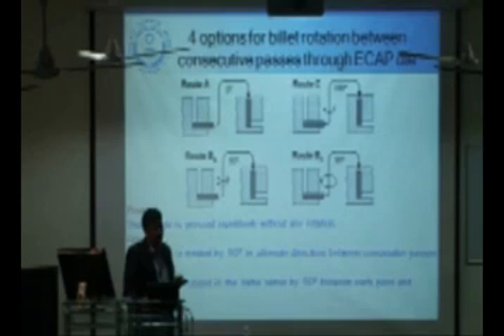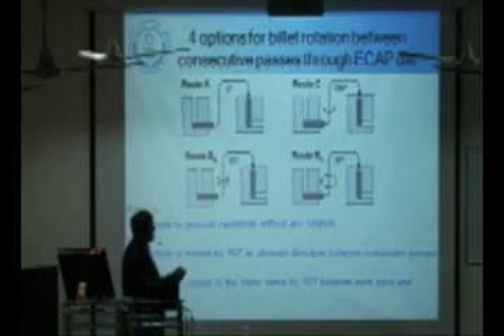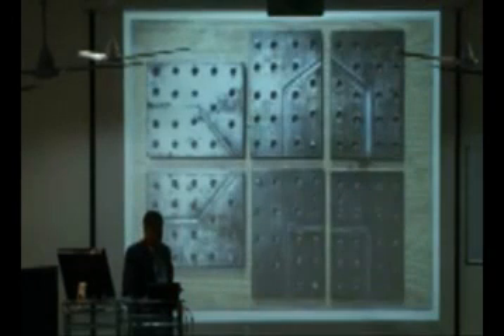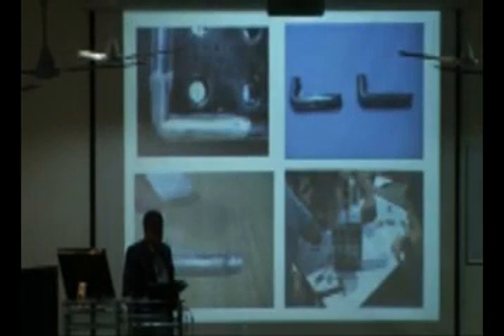Secondly, different billet rotations are used to get a uniform cross section. So route A, route B and route BC: the billet is taken, then rotated by 90 degrees and put again, then rotated by 180 degrees and put again, if you want a uniform cross section. These are the dies that we have fabricated, and we are doing experiments here. This is how the experiment takes place.